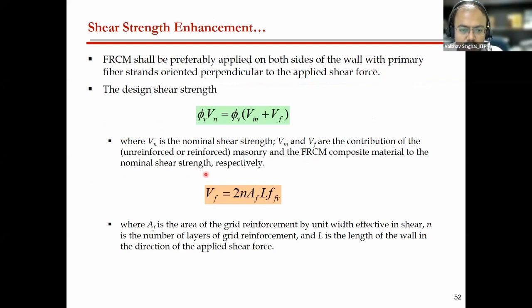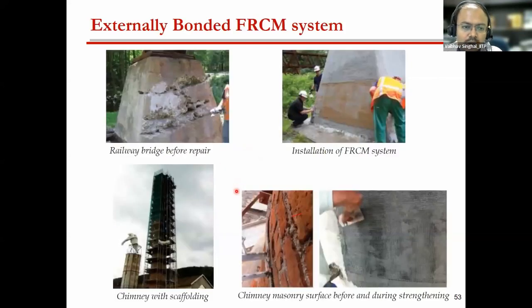So the equation suggested by the American code is quite easy compared to this Italian code. They have a very simple equation and they have suggested to use this f_fv, which they call the effective stress, that is, how much stress the reinforcing material or your reinforced cementitious matrix can take, and then multiply it with the length and area. N is your number of layers of reinforcing material, and 2 they have kept if it is applied on both sides. If it is not applied on both sides, you simply take it as 1. Now these are some of the photographs of application of these reinforced cementitious matrix.